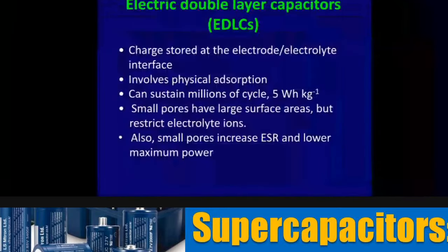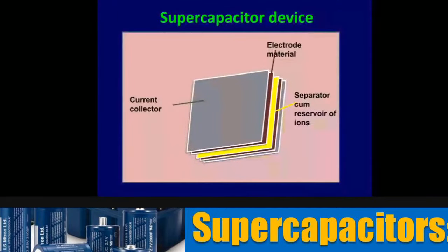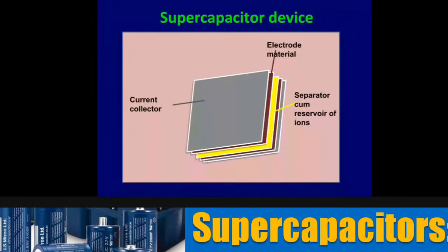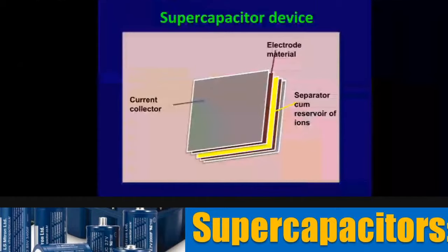When you look at the mechanism, or before the mechanism, we will see the device. Now you will see clearly that it is a multi-layer device. It is something like a sandwich made up of five layers. The two extreme ends seen in the cement color are current collectors, usually made of a metal foil or a graphite sheet. On that current collector, electrode material is coated, pasted and bound to that material. And then the yellow colored layer that you see is the separator cum reservoir of ions.